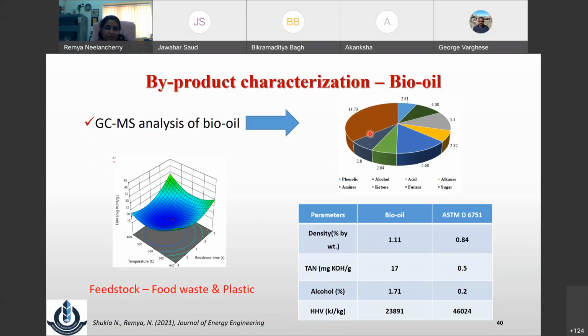So here, one important thing is that we have optimized the total acid number. Total acid number should be very low. Here you can see it is around, sorry, it is 17 or so. The higher the acid number, the higher the corrosivity. But most organic waste is not meeting the TAN standard. But when you go for food waste combined with plastic pyrolysis, the two in a microwave system, we could give a better quality bio oil compared to conventional biomass pyrolysis. But even then, it is not meeting the ASTM standard for use as a biofuel or gasoline. Of course, this can be used as a burner fuel for a heat exchanger or so.